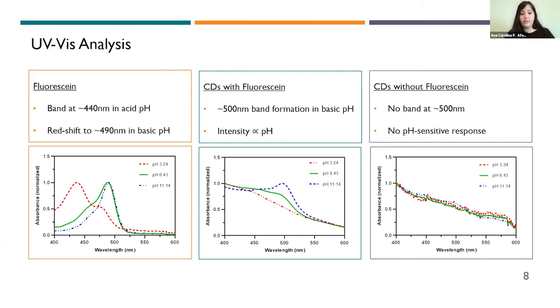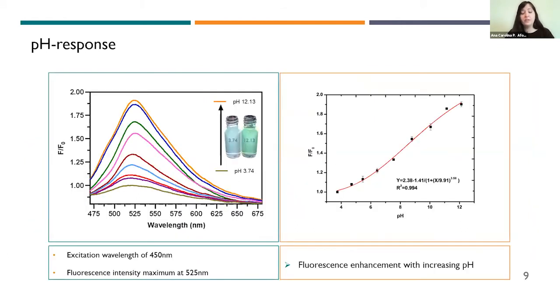On the other hand, the UV spectra of the carbon dots without fluorescein does not present a band at around 500 nanometers nor a pH-sensitive response in this region of the spectrum. The fluorescence wavelength maximum of the carbon dot with fluorescein was 525 nanometers, which is similar to standard emission profiles of fluorescein. And furthermore, as seen for fluorescein, the carbon dot undergoes significant fluorescence enhancement with increasing pH. This data was then fitted with a logistic function with a correlation factor of 0.994 within a wide range of pH values from 3.7 to 12.